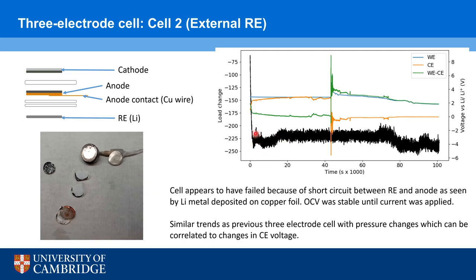an initial increase, which is correlated with the increase in the open circuit voltage of the silicon anode, as the electrolyte percolates through this nano composite electrode. As the electrolyte percolates, the open circuit voltage should increase as the ohmic resistance decreases. And then again, we had this slow buildup of pressure as this native SEI forms and the binder swells.